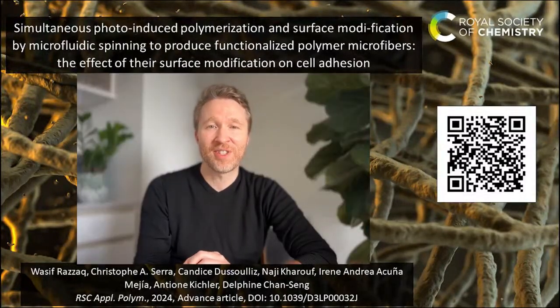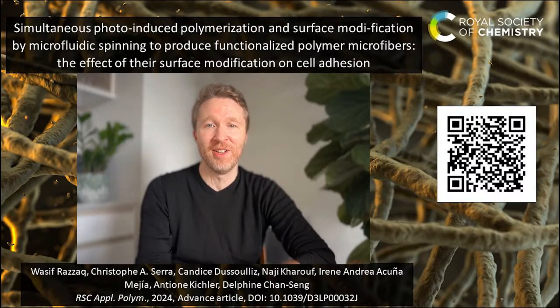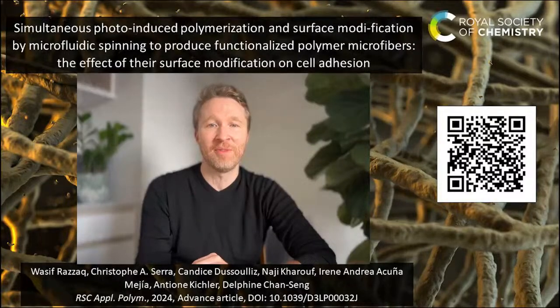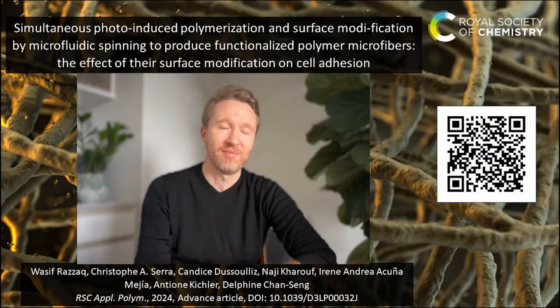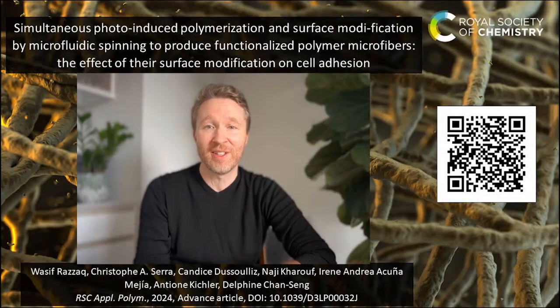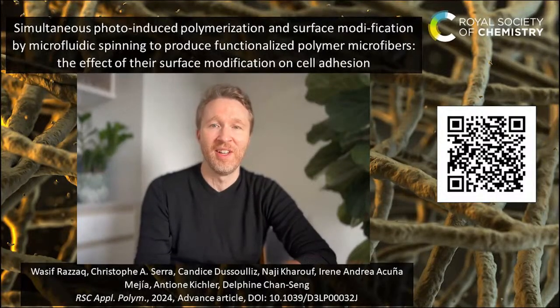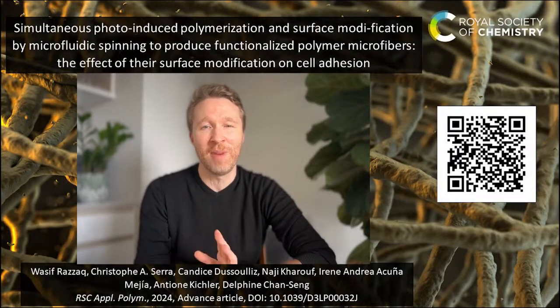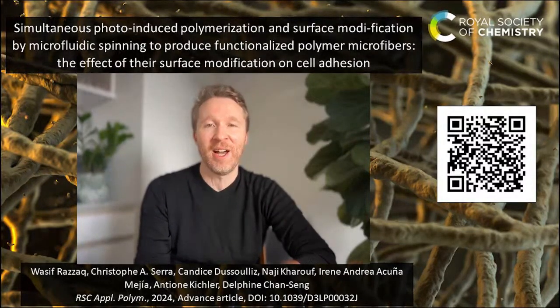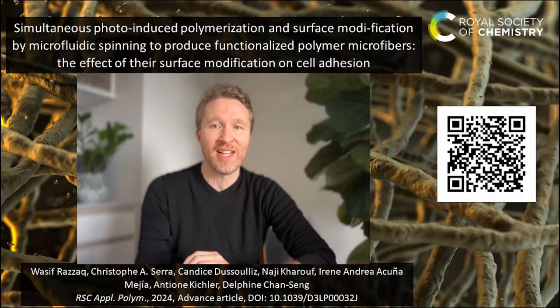I thought this was a very interesting and impactful approach because usually the modification of microfibers is done in a post-production step. But this paper reports for the first time the production of polymer fibers that can be functionalized in a one-step process. This reduces cost and time needed to obtain these functionalized fibers, and the potential use cases are very broad. Everywhere where you need functional groups on the surface of polymer microfibers, for example in biomedicine, tissue engineering, but also in non-bio-related applications like fiber optics, sensors, or water treatment.